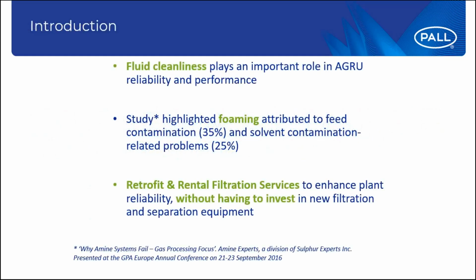Fluid cleanliness is an important topic, and it plays a paramount role in acid gas removal units in terms of reliability and performance. A vast study conducted by amine experts highlighted foaming is attributed mainly to feed contamination in 35% of cases and solvent contamination related problems in 25% of the cases. If you consider these two main root causes, you see that the attribution of foaming causes is more than half that is covered here.